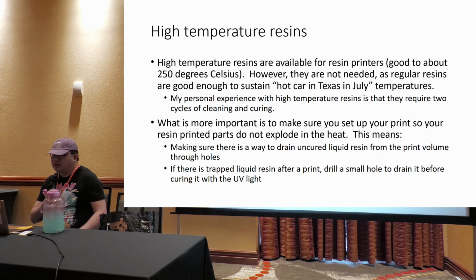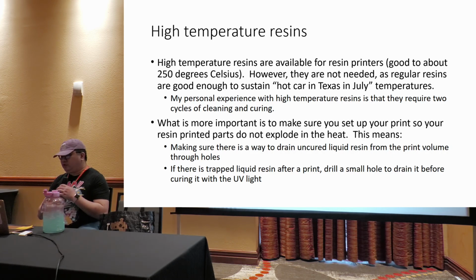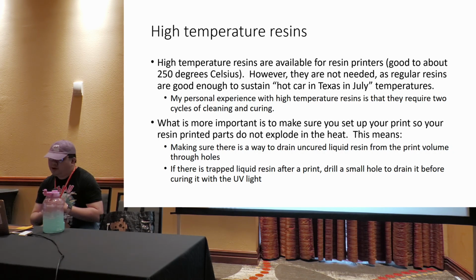But in general, if you choose to use high temperature resins, in my experience, when you do a resin print, you know you have to wash it and cure it. You will have to do it twice for a high temperature resin, or else it will not fully clean itself. There was one part I only did once, and it felt a little bit fuzzy, and paint wouldn't stay on. After I washed it the second time, things went okay. So just wash and cure it twice.